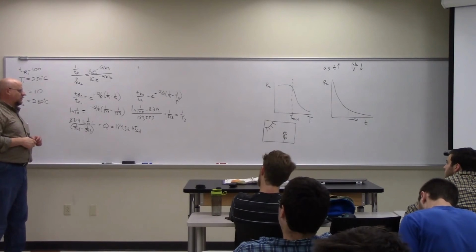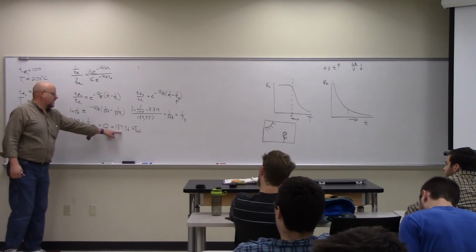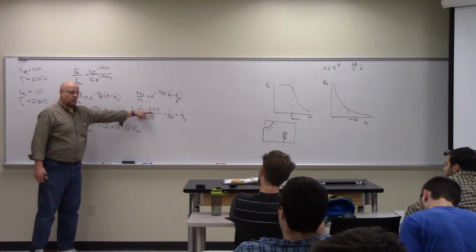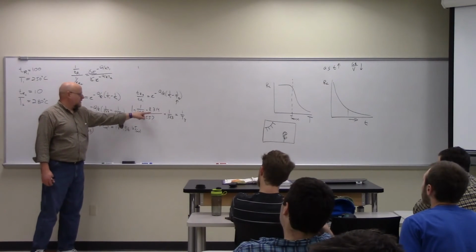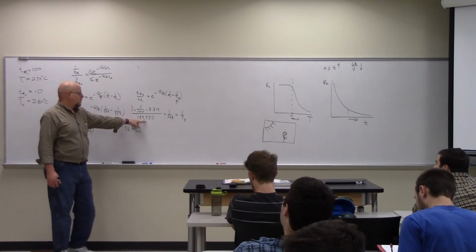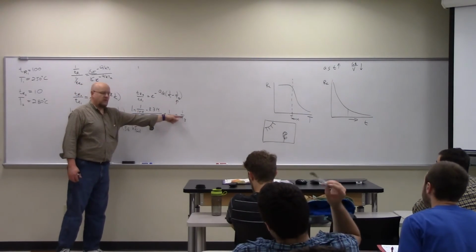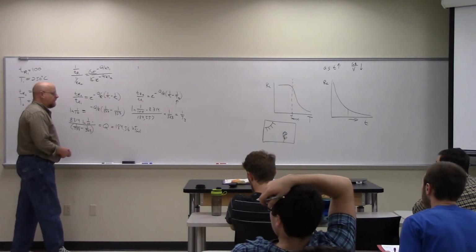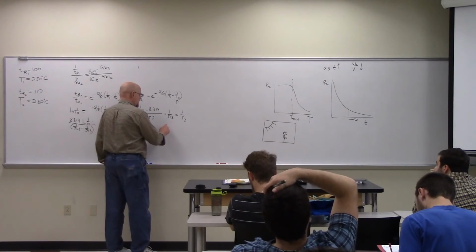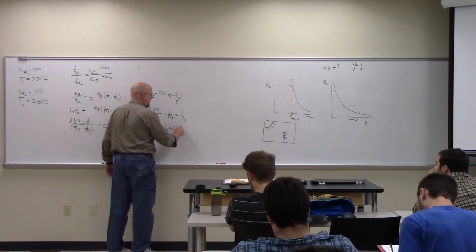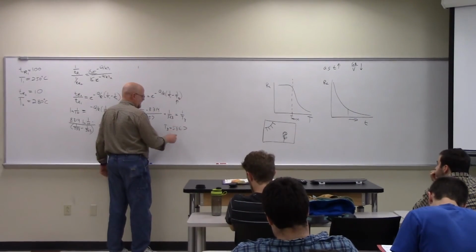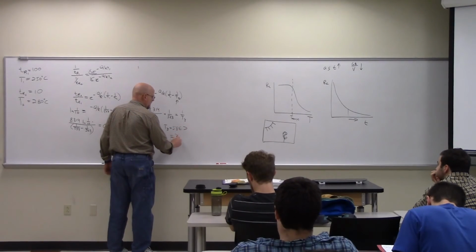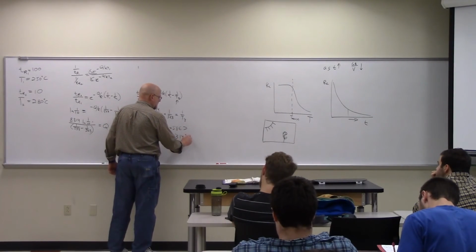So what do I get there for T3? Does anybody get that? 184,557. I'm doing it in joules because that's in joules per mole. This is in joules per mole Kelvin, and this is in joules per mole, so I end up with per kelvins plus per kelvins equals per kelvins. I get T3 equals 586.7. So 587, which when I subtract the 273 is 314 degrees C.